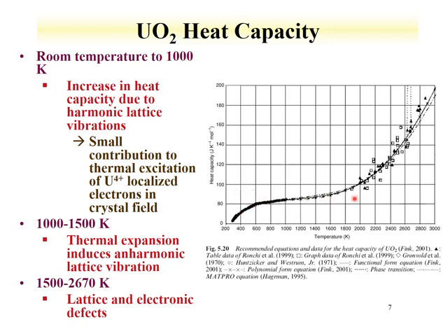Above 1,000 degrees to about 1,500 degrees, right about here, we start to introduce anharmonic lattice vibrations. So this is a very simple lattice. This is anharmonic. So this is changing the system. We see a slight change in the behavior of the increase of heat capacity. And then above 1,500 K, we start to introduce defects, and we see a very, very large increase in heat capacity at high temperatures.